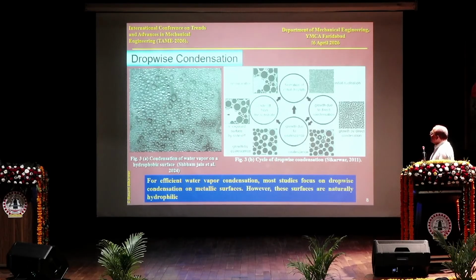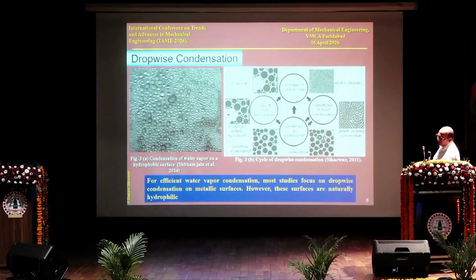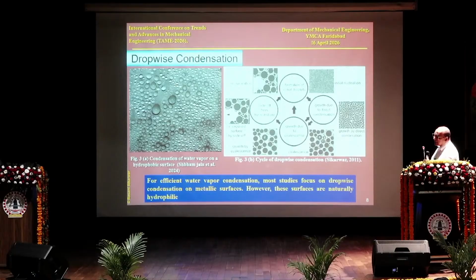But when you see it, it is a continuous process. There is the formation of the droplet at a specific nucleation site, which is called nucleation. Then growth by direct condensation, then growth by coalescence. Then it slides off, re-exposing the surface for recondensation.